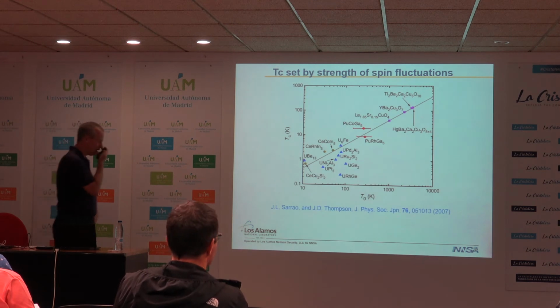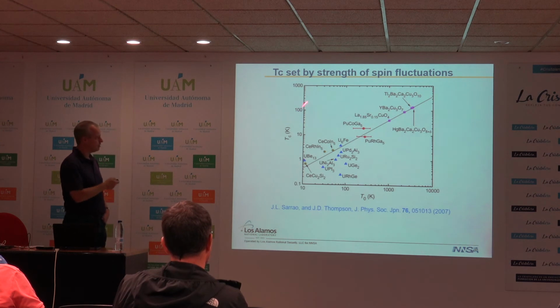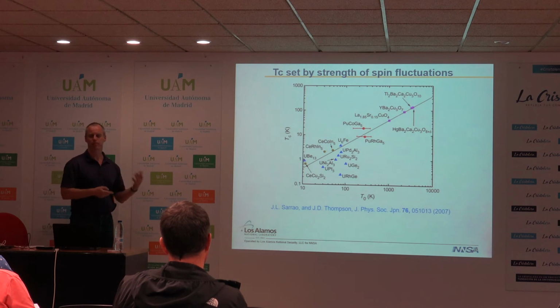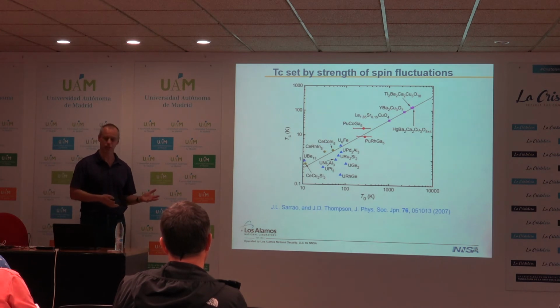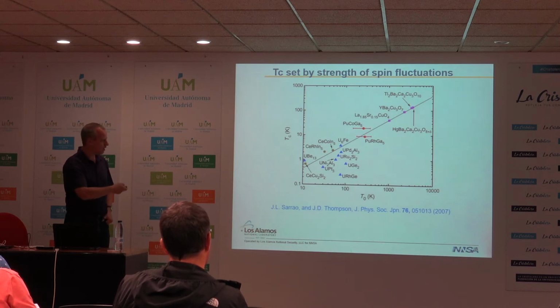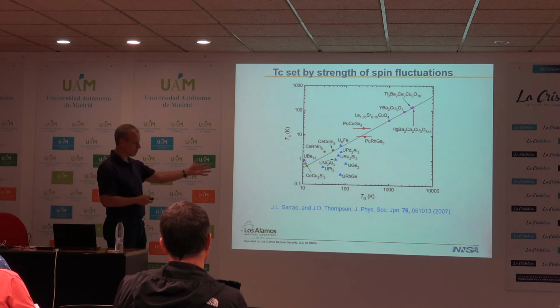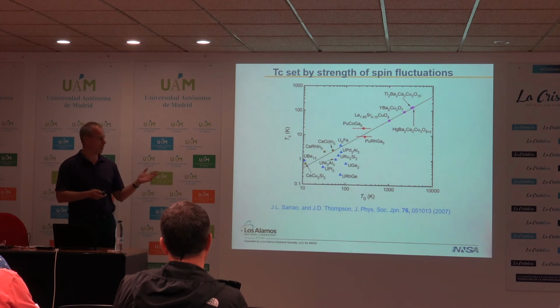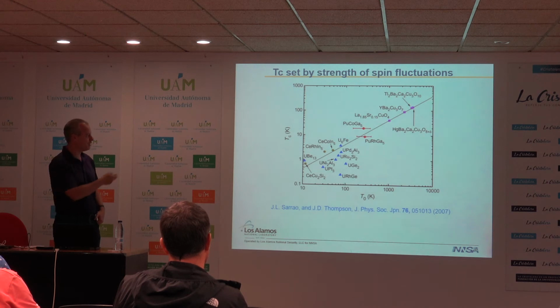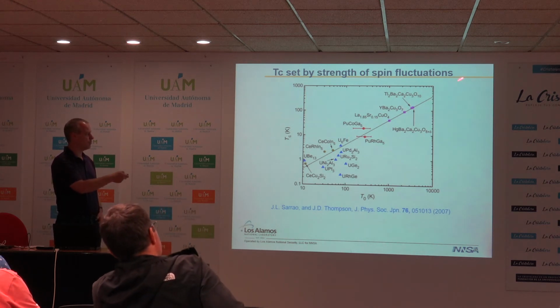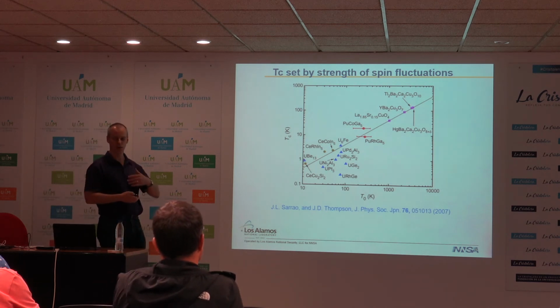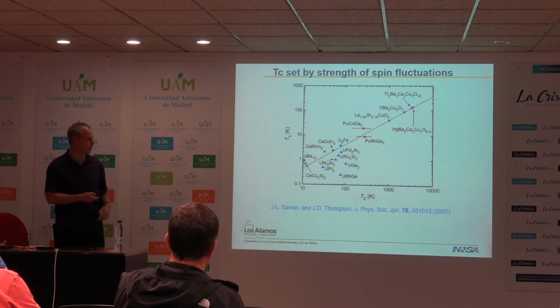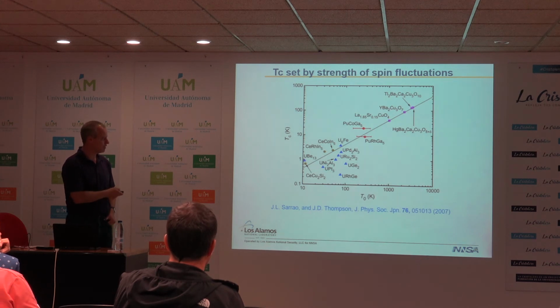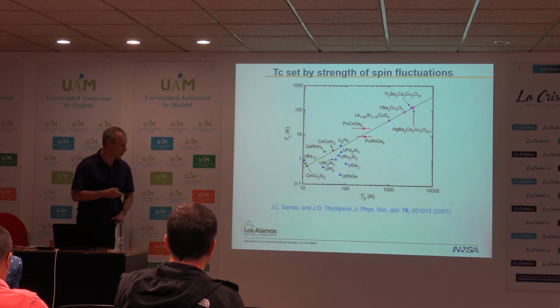Okay, so this is a plot to really show that the superconducting transition temperature seems to be set by some spin fluctuation energy scale, one that you extract from the electronic degrees of freedom. In this plot, it's a log-log plot, and we should always be cautious about over-interpreting, especially when there is a fair amount of scatter. But roughly speaking, you can extract a spin fluctuation energy scale from the NMR, from the specific heat, even, in the cuprates, from the T-linear term of the resistivity, but you could extract it in other ways. You see all these compounds roughly fall on the line that says the characteristic energy scale of the spin fluctuations coupling to the conduction electrons is setting the scale for TC in all of these compounds. And the ferromagnetic superconductors sit a little bit below this relationship.